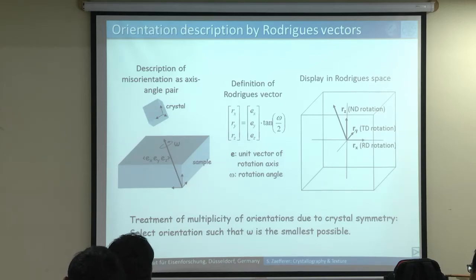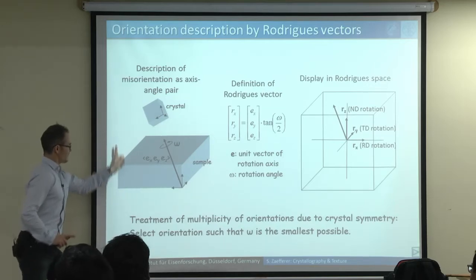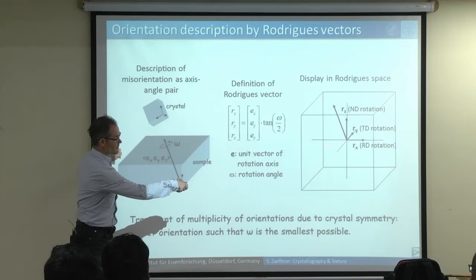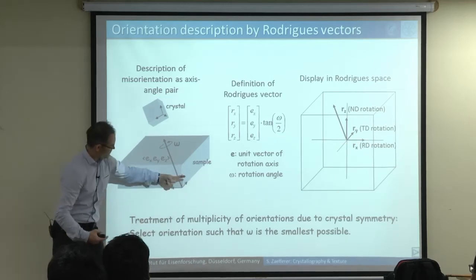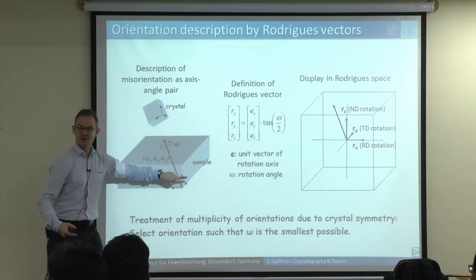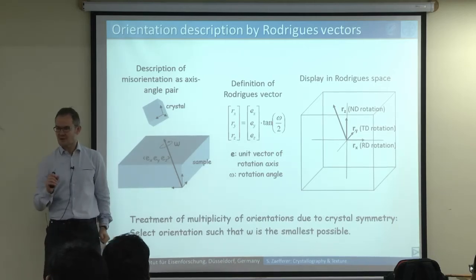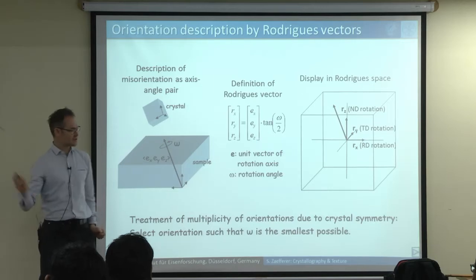And furthermore, as I show it here, if you just have a coordinate about the first vector, the Rz, then this corresponds to a rotation about this angle here, about this vector here. If you have a component only about x, it only contains a rotation about this direction. So it's actually quite easy to understand this space. It's easier to read.